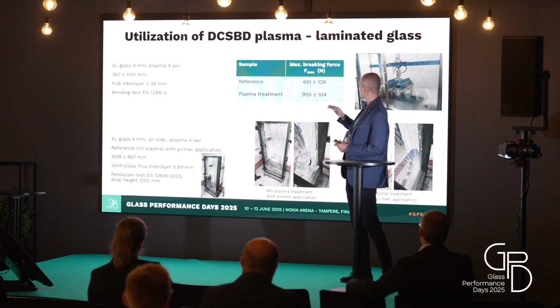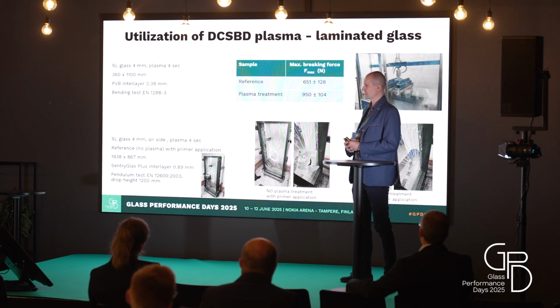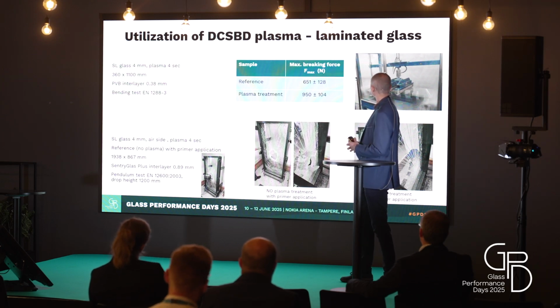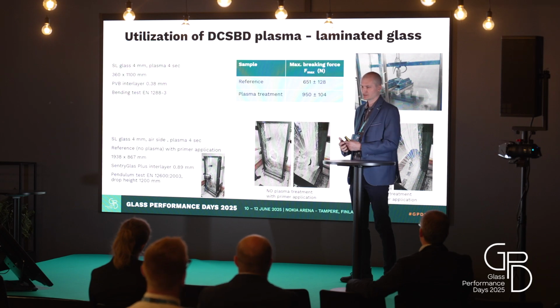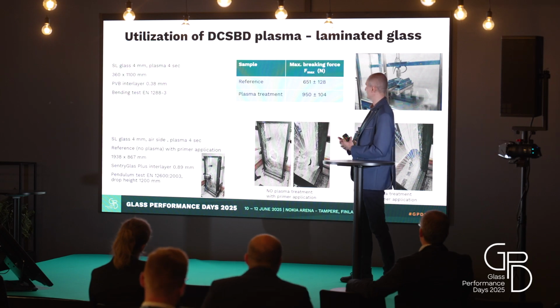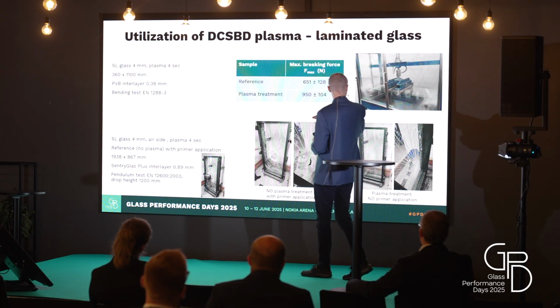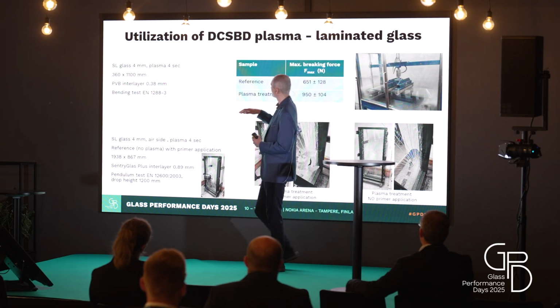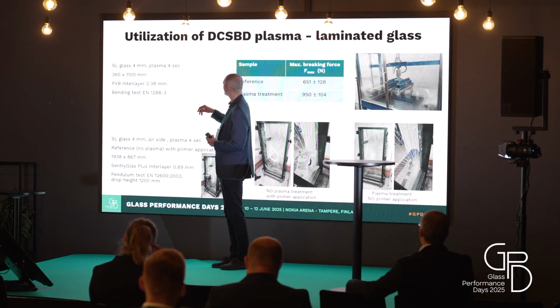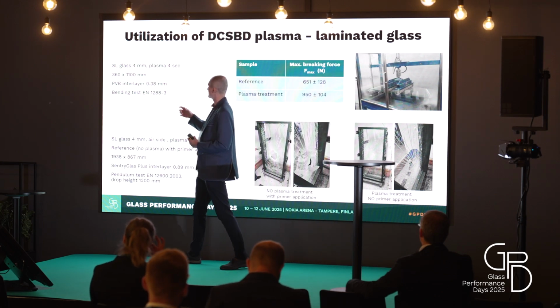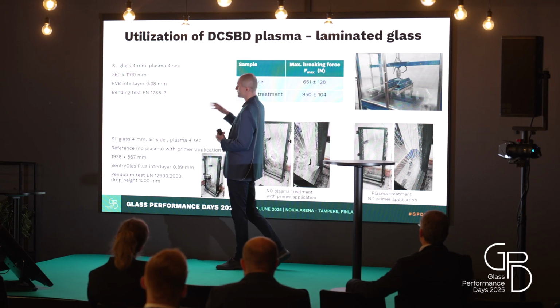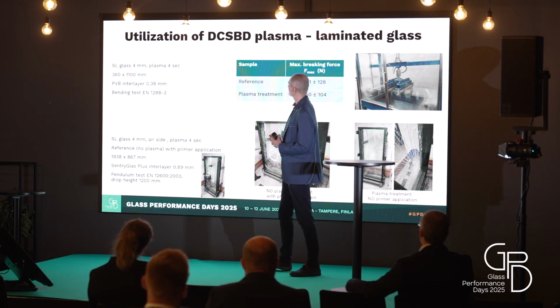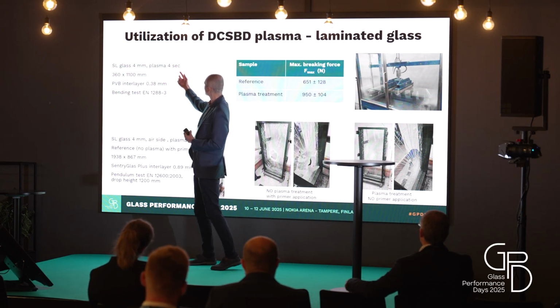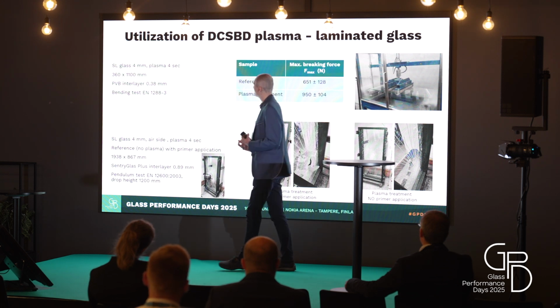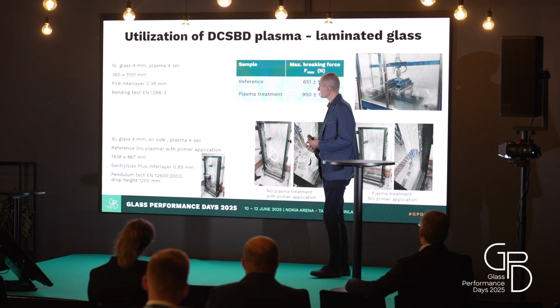So let's treat our glass panes by our plasma and we can utilize it for laminated glass samples. I have here a couple of results. We created laminated glass with standard soda-lime glass. We can work with the air side or the tin side. We treated the samples with a very short treatment time, just 4 seconds.